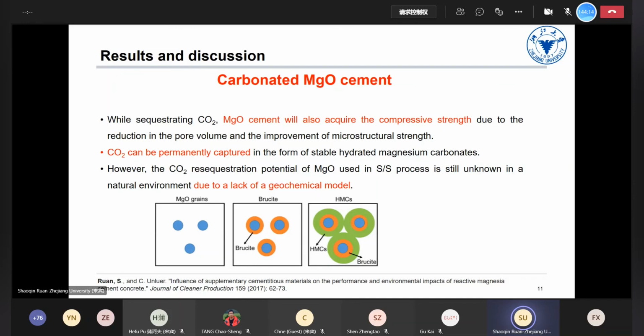And you can see from this figure, the MgO will first react with water to produce some layers of brucite on the surface of the particles. Then it will further react with carbon dioxide to produce the HMCs, that is, the hydrated magnesium carbonates. And then it will lead to the filling of the pores and the strength improvement.